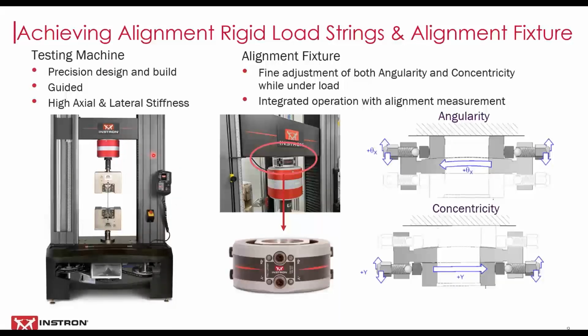Those are the characteristics of the testing machine that we require, and then we can augment that with an alignment fixture, which mounts between the crosshead and the load cell. Here we see this would be sitting here. This is the alignment fixture, and this is really a vernier adjustment for angularity and concentricity. So it gives us very fine control over the angularity and concentricity on the machine, and we can use it to adjust the load string until the alignment is very good.